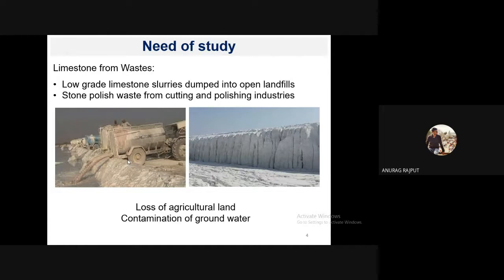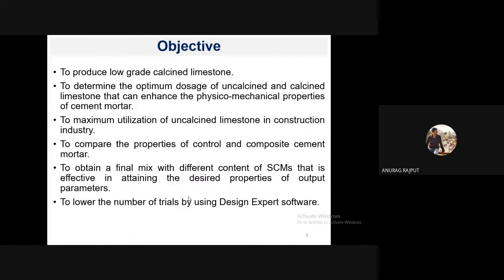There are a lot of sites in Rajasthan where this low-grade limestone slurry is dumped into open landfills, which degrades the land. And this is the picture of Rajasthan where it is dumped into the open landfills. Also, stone polish waste from the cutting and polishing industries is dumped into the open landfills. This is the picture of the deposition of this slurry, which is huge. The impact of this slurry in the open landfills leads to the loss of agricultural land, which contaminates the groundwater.